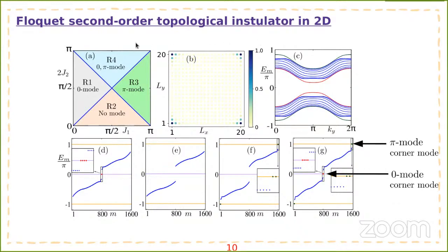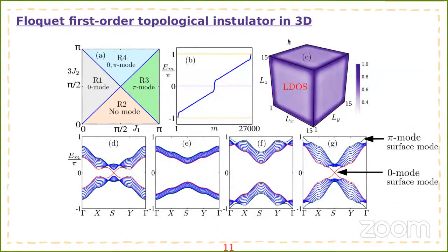Now we set alpha not equal to 0, as I have told. There I can get the second order mode, but here interestingly the phase diagram remains the same, and to get the second order modes, one needs to go to the open boundary condition in both directions. If we diagonalize the Floquet operator considering open boundary condition in both directions, you can see that in the eigenvalue quasi-energy spectra there is a 0 mode as well as a pi mode, and the modes are populated around the corners of the system, and it is expected that the edges should be gapped. So if we plot the eigen spectra following the ribbon geometry, you can see that both 0 and pi edge modes are gapped.